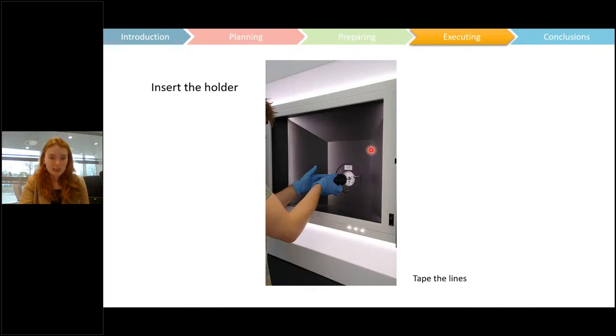So you would then insert the holder, and that's obviously a very important step. And we generally attach the lines in, and then we run a leak check on those lines, the lines to the back of the holder. I run a leak check on those lines every single time. And the reason why I do that is because those lines are new every single time you assemble the holder. So if you have a leak, you have no way of knowing it until you've ruined your experiment. So those lines get checked as the first thing on every single experiment. I don't necessarily do the 10 minute leak check, but I do pump it down to like 0.01 millibar. If it goes down that far, then you know that it's tight.